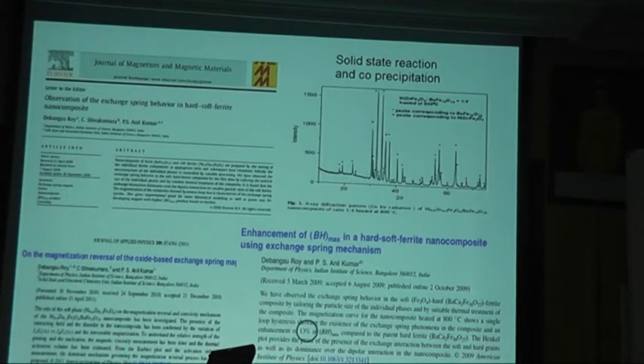And then here are the different papers. They claim that the BH max can be enhanced by up to 13% after they combine soft and hard. I tried to check the grain size for this, because in solid state reaction it's difficult to get below 50 nanometers.